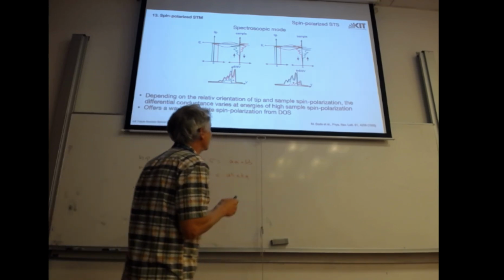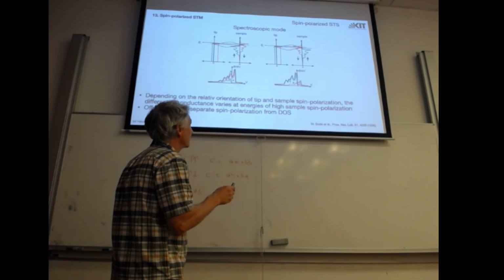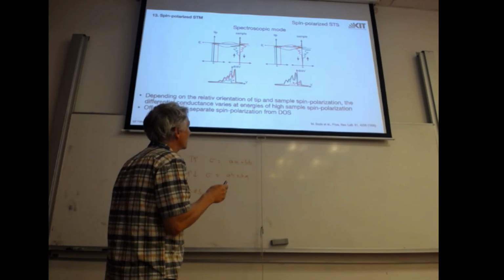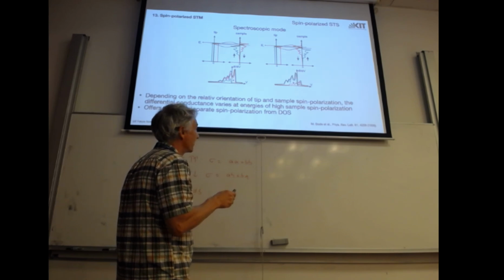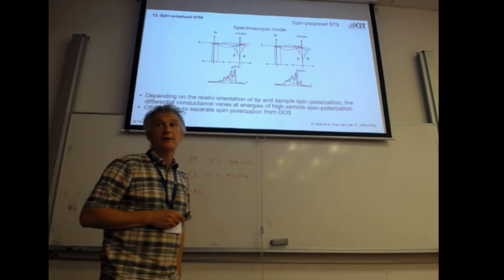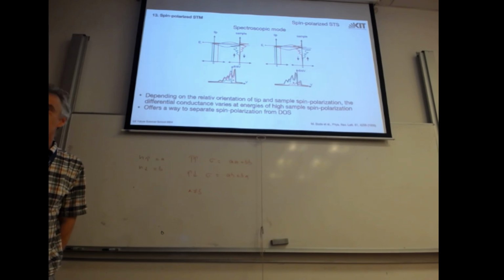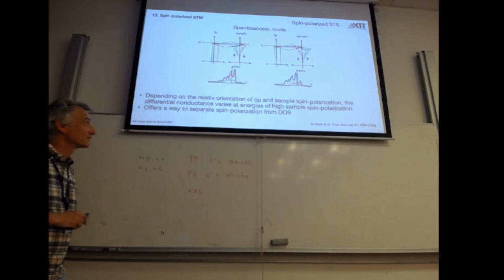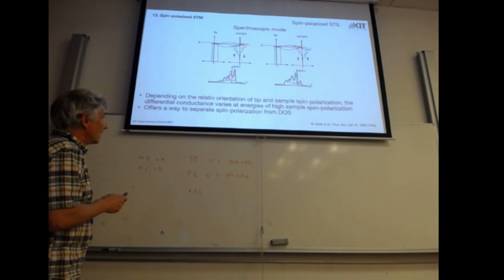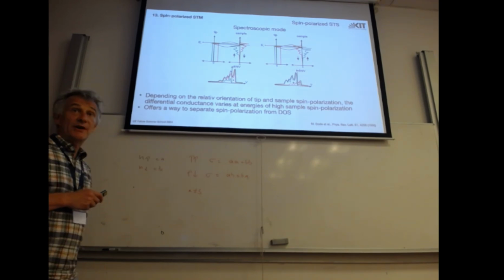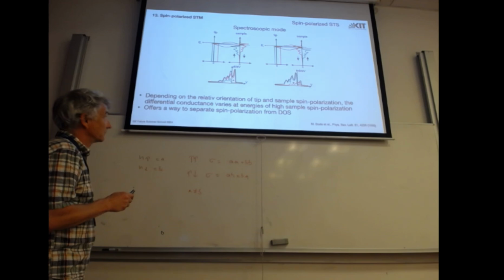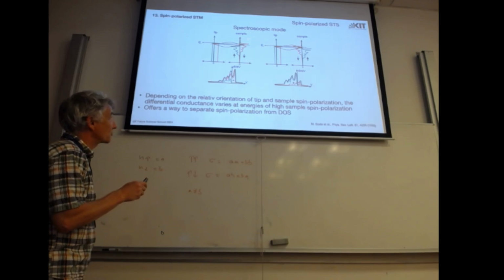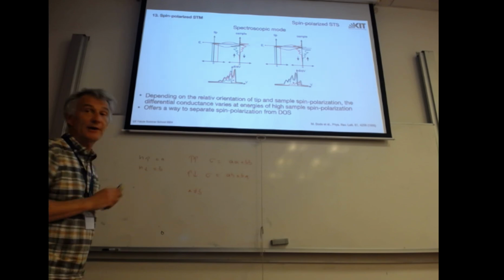And the anti-parallel configuration is now tunneling from green to red and red to green. So now the green curve will be weighted more than the red curve, and you see the difference in the spectrum. Yeah? And how do you create polarization inside the tip? Ah, you take just a magnetic tip. Okay, but I will show you examples. So that means with the additional variation of the energy, the IV, and you choose peaks which are spin polarized in the density of states, then by the peak height, you can decide if you are parallel or